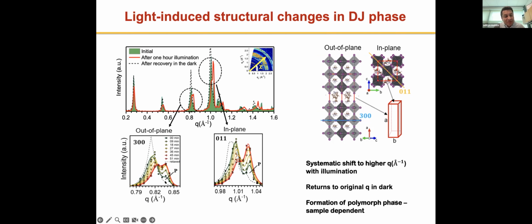In addition to this, we also see another little phase, which is marked as a P here, which emerges and starts to get stronger. However, what we found is that this phase is not as reproducible and is very sample dependent. We think this is some kind of polymorph phase, which tends to occur when a very specific type of sample is being used. It wasn't as reproducible, so I won't really talk about this specific polymorph phase, but we will focus on this effect of light-induced contraction in these materials.